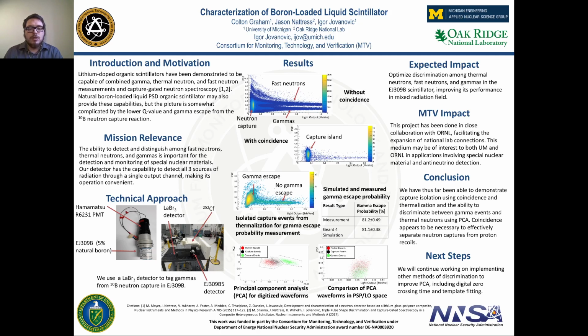As a preliminary result, we've been working on using principal component analysis with the digitized waveforms of tagged events to try to better isolate capture events. You can see pictured here a series of gamma events shown in green, capture events shown in black, and fast neutron events shown in red, which are displayed in principal component space. And you can see using this, we're able to achieve much better discrimination between the gamma events and the capture events using principal component analysis.